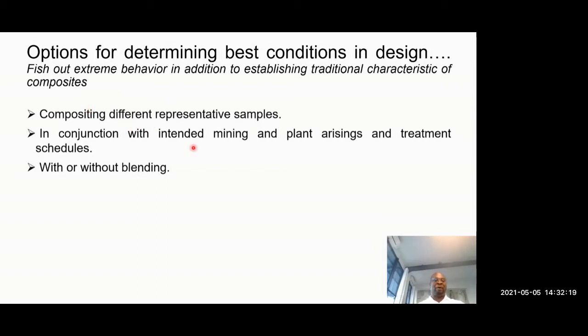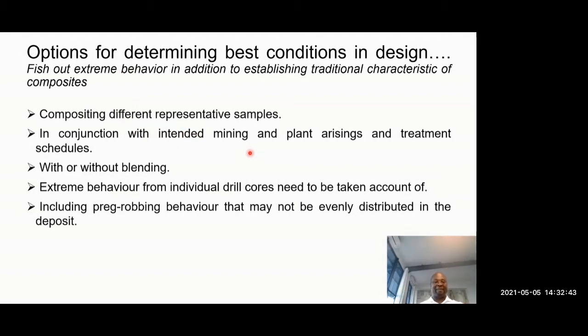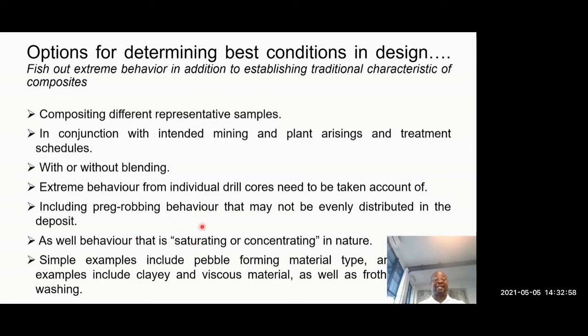Now, what we obviously will do is compositing of different material from the mineralogically different zones and do testing for the bulk or residence time and those sort of other issues. But you have to do that obviously in conjunction with the intended mining plans and plant arisings. That's typically done now, with or without blending. But what I'm saying is that extreme behavior from individual cores needs to be taken account of, including things like preg-robbing behavior that may not be widespread within the whole circuit, or may not be evenly distributed in the deposit, as well as behavior that I call saturating or concentrating in nature.